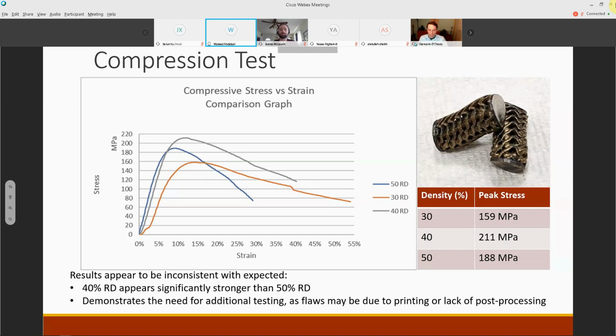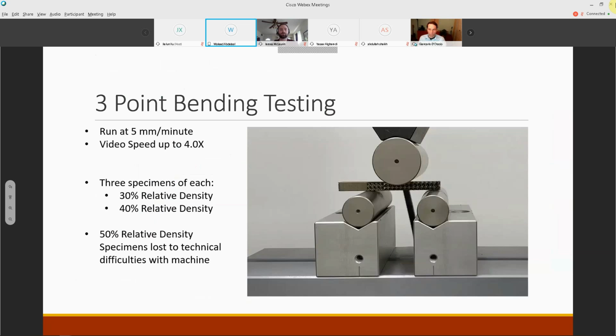These results appear to be inconsistent with what was expected, since the 40% appears significantly stronger than the 50%, and this demonstrates to the team the need for additional testing, as flaws may be due to printing or lack of post-processing. So this next test is our 3-point bending test, and we have 3 specimens of each.